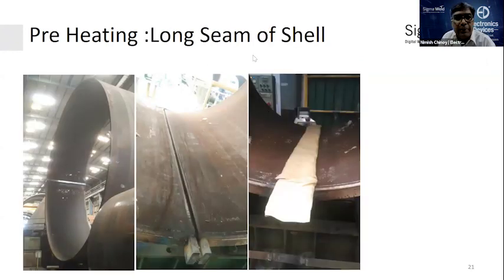You can see long seam preheating of a shell happening. So this is a typical seam you have to weld. It's about 70 thick, 3 meters long. To do this, they were taking about 20 to 30 minutes to set up the resistance heating coils. And then it would take about 2 to 3 hours to achieve the temperature of 150-200 degrees.